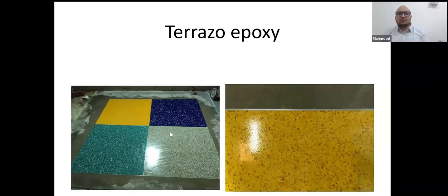Epoxy terrazzo with the epoxy base and hardener, then filler and glass beads. Based on the requirement, you can modify according to the site condition. This is how it looks glossy after grinding and polishing.